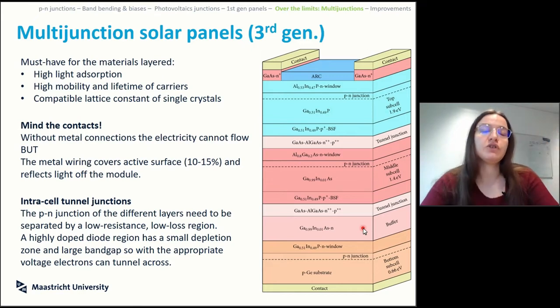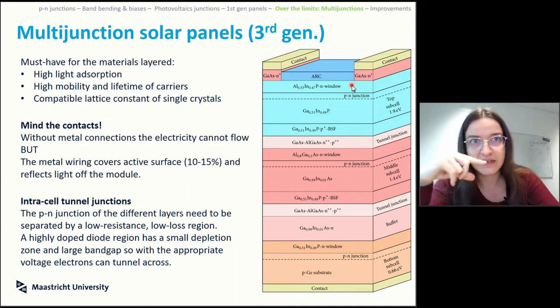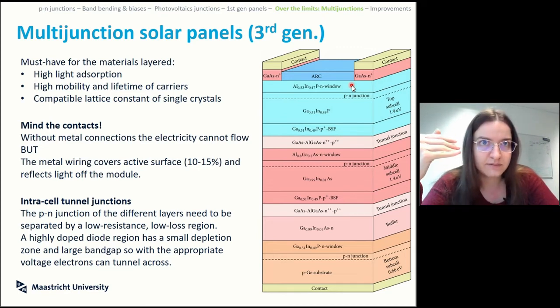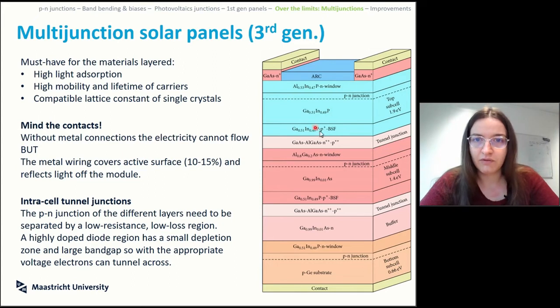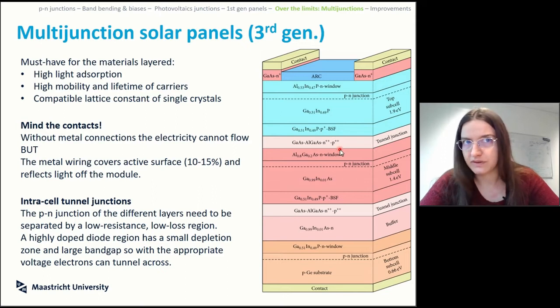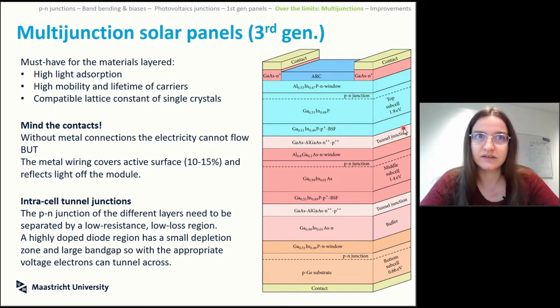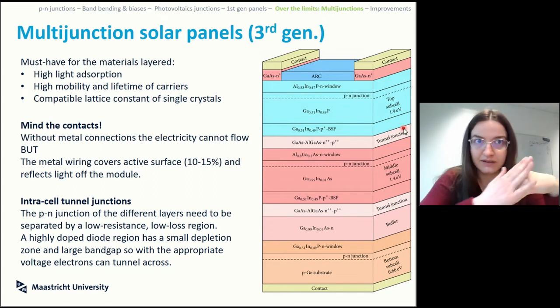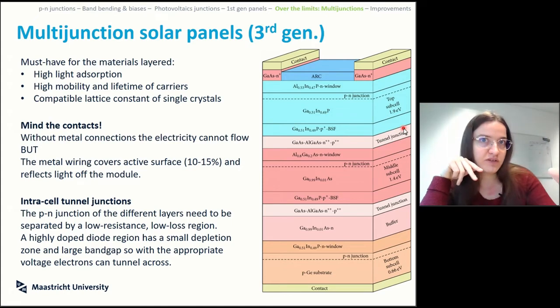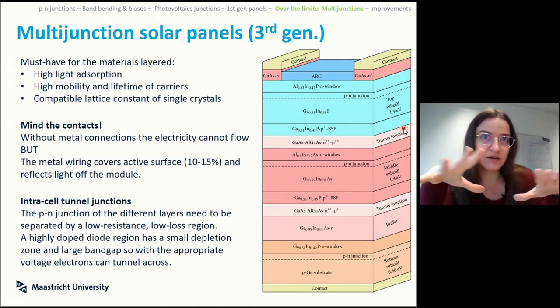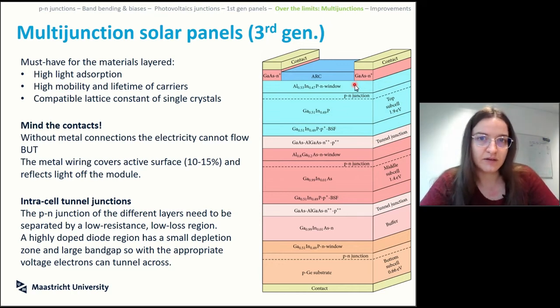So this is the point in which you actually use that trick of layering the p-n junctions differently from just p and just n, and when you do avalanche type of tricks. Because then you avoid, instead of having just the p and the n, when you look at the materials that we have in this layer, you have points that are very highly doped, and depending on how you dope them, it means that the passage in between is unhindered and incredibly fast. You create tunneling because you have that super strong potential. The electron will just see the passage through and will get unhindered by anything else. But the concept remains fundamentally the same.